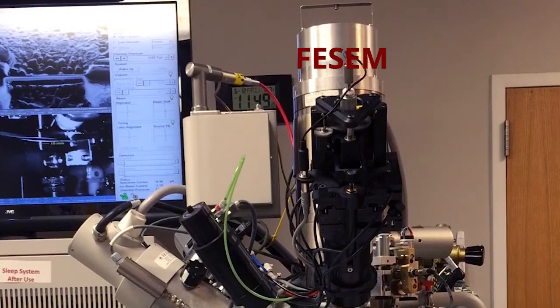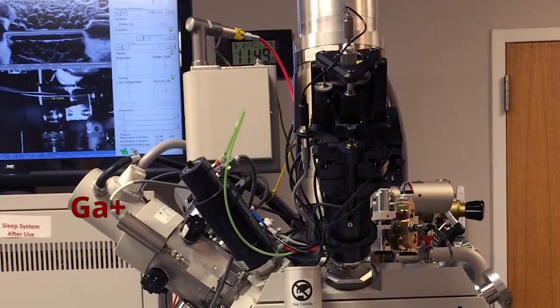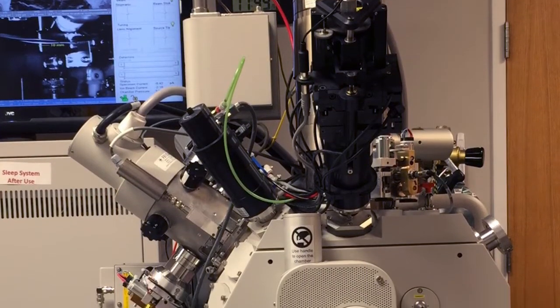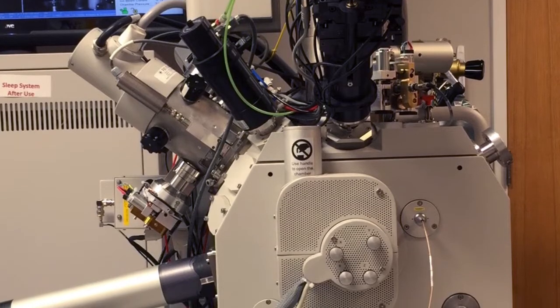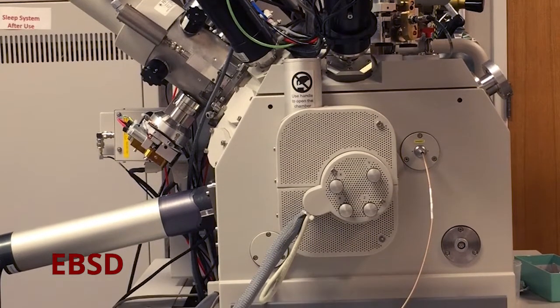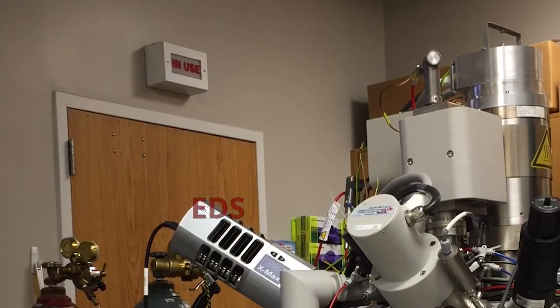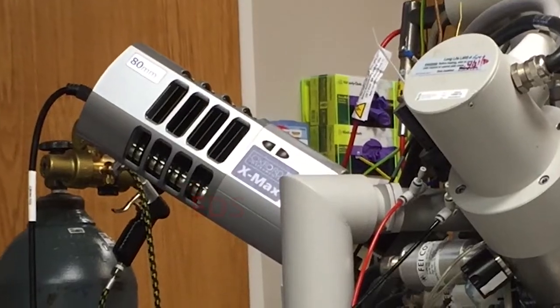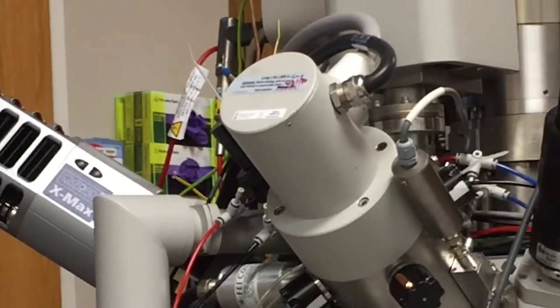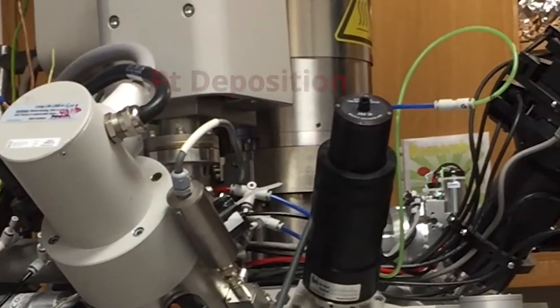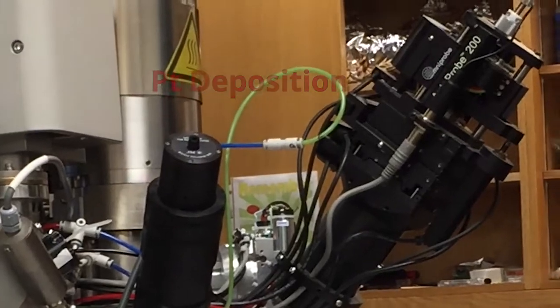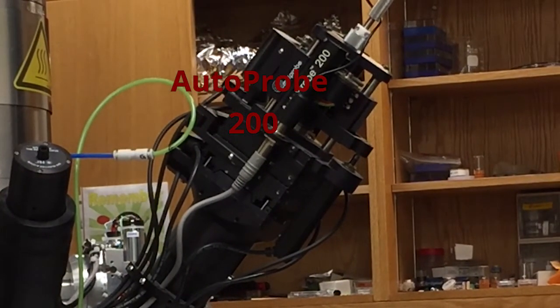Hello, I'm Roberto Garcia. I'm the Operations Manager and the FIB Lab Manager here at the Analytical Instrumentation Facility. Behind me is the Focused Ion Beam Instrument, or the FIB for short. The system is equipped with a field emission SEM column and a gallium ion column. The unit also has several detectors, which includes an EBSD detector for orientation imaging and an EDS detector for elemental information. The FIB also has a platinum gas injection needle for deposition and an AutoProbe 200 lift-out needle.